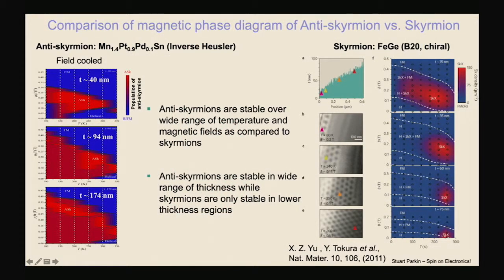On the right-hand side, in a B20 chiral iron germanium system measured at RIKEN in Tokura's group, they found that as they increased the thickness just slightly, the red region, which is the skyrmions, again as a function of temperature and perpendicular field, this region shrinks even as the thickness is increased from 15 to 75 nanometers, almost disappears. On the left-hand side, you can see great stability of antiskyrmions as a function of field and temperature. So why is this?